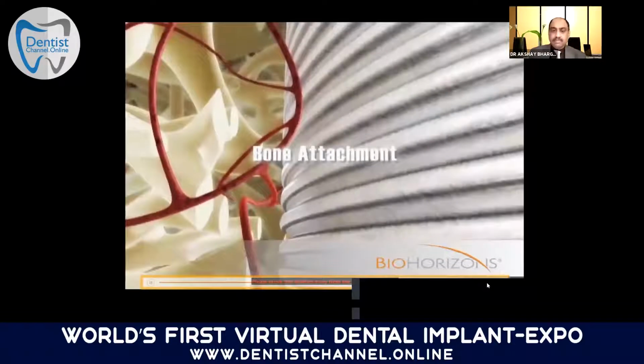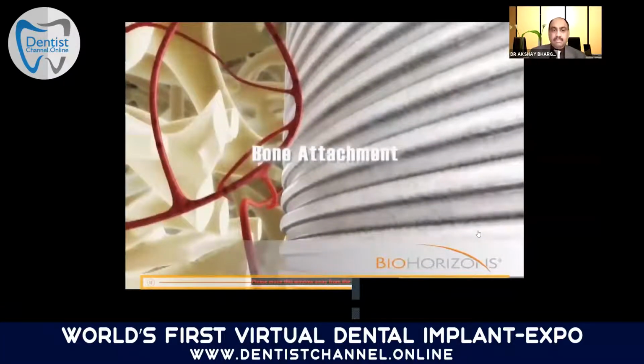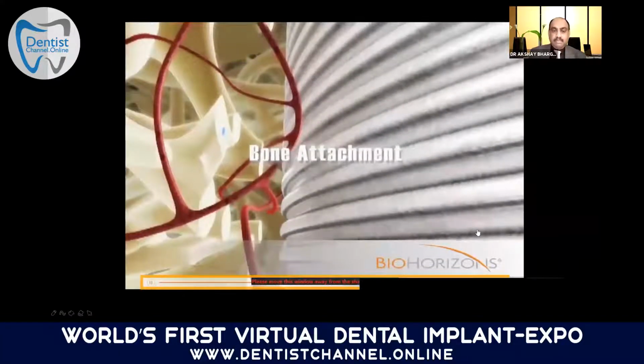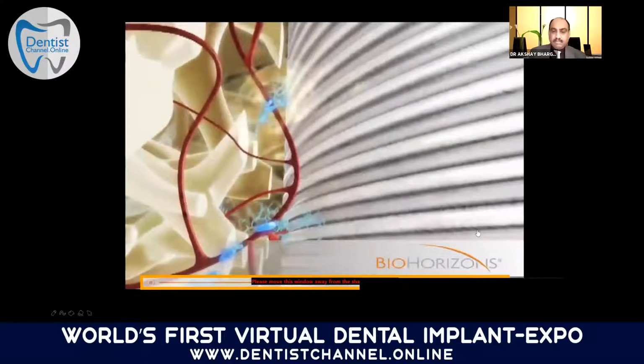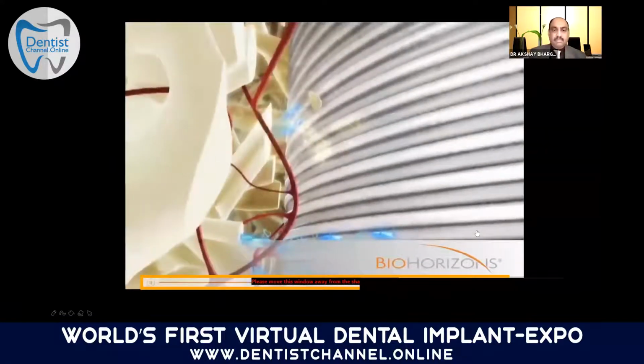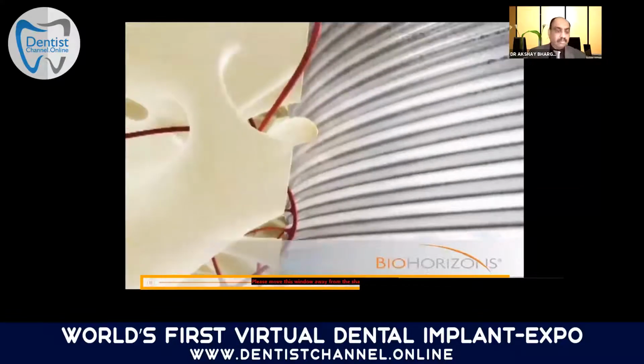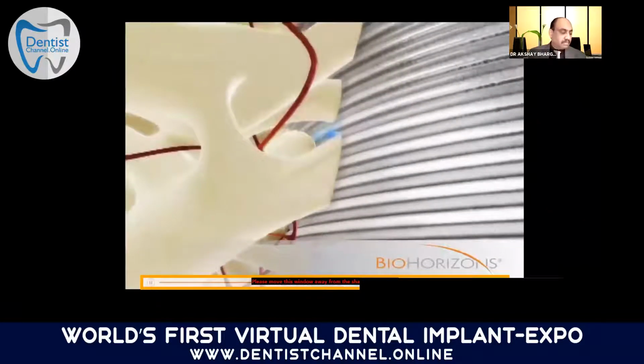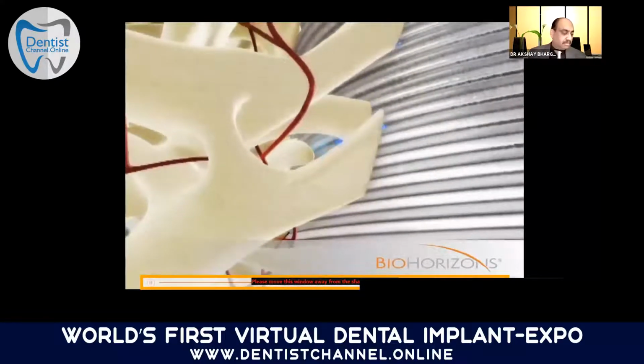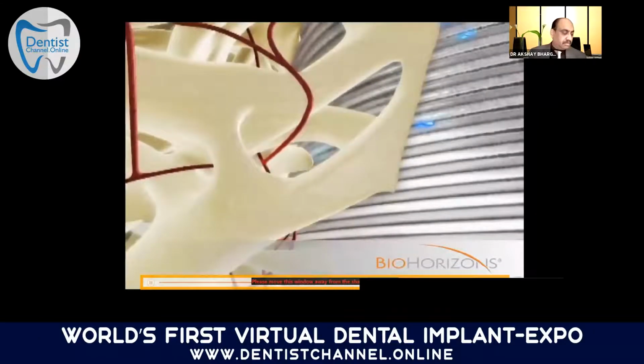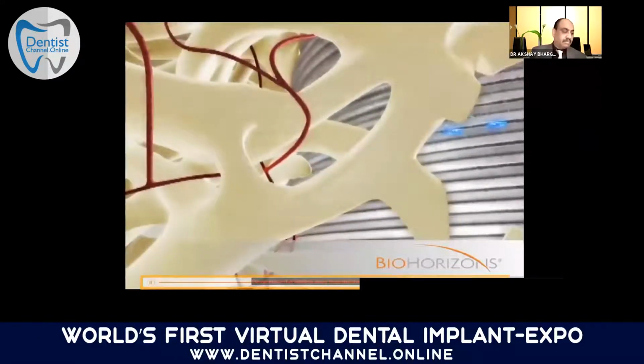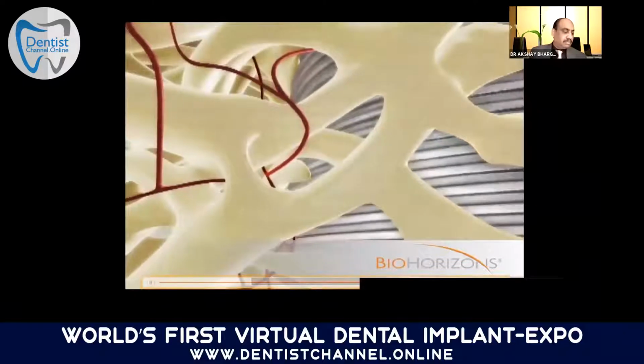Once a stable soft tissue seal is created, osteogenic cells migrate along the implant surface and are directed into the Laser-Lok microchannels where they attach and differentiate. Osteoblasts begin to form a circumferentially oriented bone microstructure with trabecular attachments parallel to the microgrooves. These structures mineralize during normal healing.